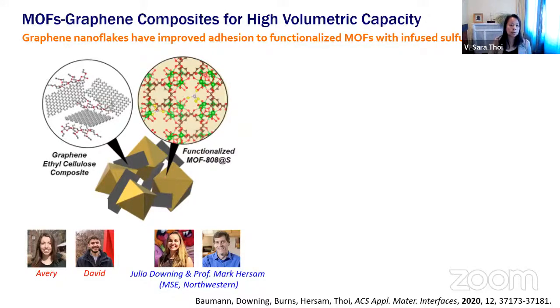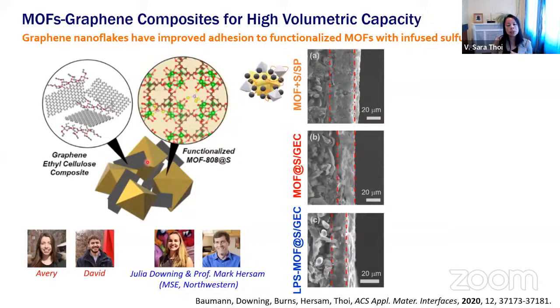So the first thing we did is that we took our metal-organic framework and we decreased its porosity by melt infiltrating sulfur into its pores. So we no longer have this physical mixture. The sulfur is actually embedded. We also use graphene materials so that the graphene's flatness could actually allow for higher charge conductivity to our polyhedron type battery MOF particles. And what we show here is that the physical mixture of MOF plus sulfur plus carbon actually yields a relatively thick electrode.